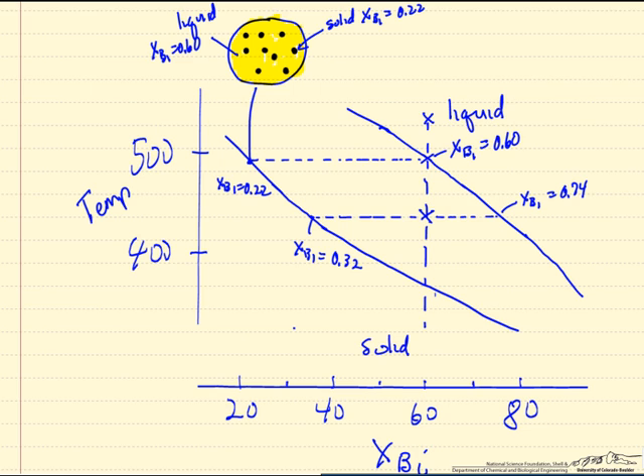That's the equilibrium value. However, when this happens, the solid that had already formed doesn't immediately mix and have rapid diffusion, so we form a solid around these solid particles.